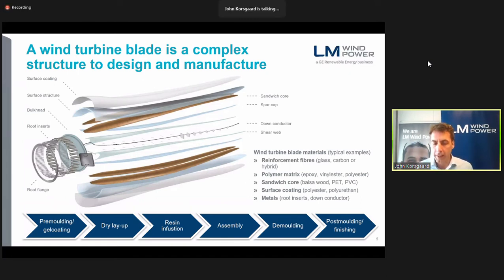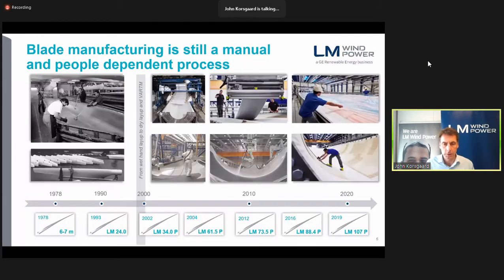The molded blade is released from the mold and then transported into the post-molding finishing area, where the final finish of the blade is performed and where 3 blades are matched into one set of more or less identical blades. So that's the build-up of a blade and the manufacturing process.